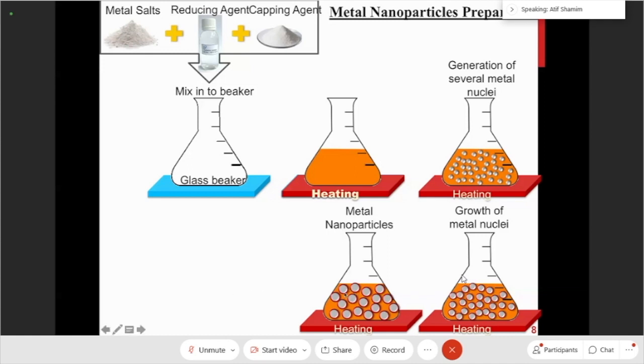But before printing, you don't want them to form big lumps, right? Because then it will not be possible to print them through those fine nozzles of the printers. From the nozzle, you still want it in a very liquid form, so that you could pass through those nozzles. But after it is printed, then we basically get rid of these capping agents. I will tell you in the next slides how to get rid of them. And then these nanoparticles mix with each other to form continuous traces.